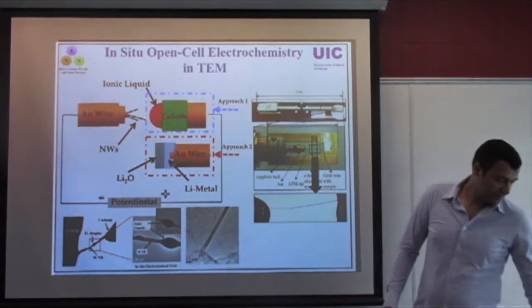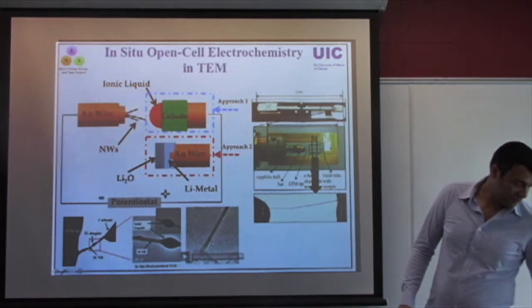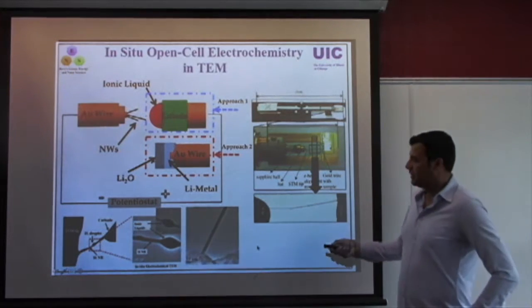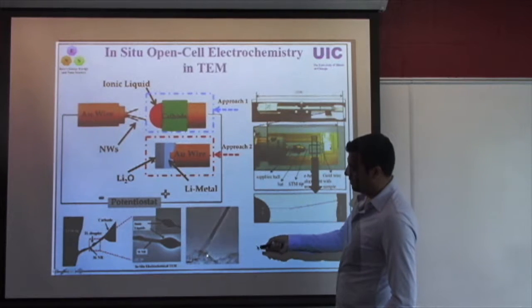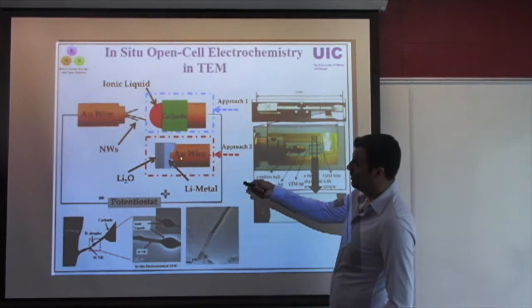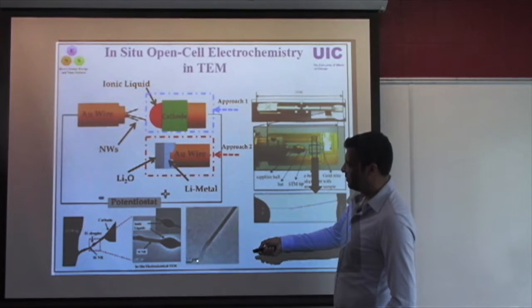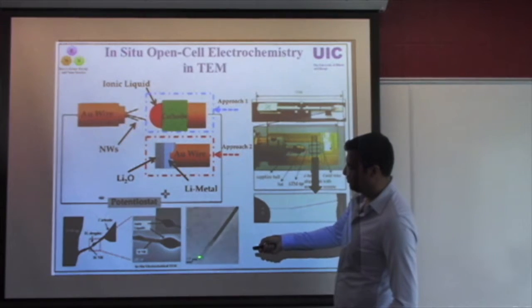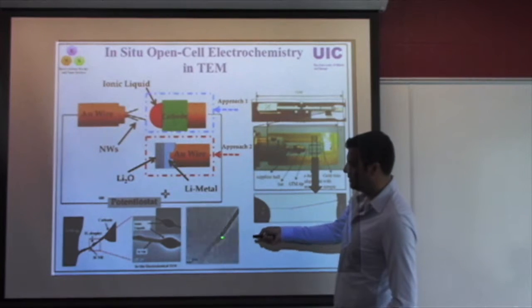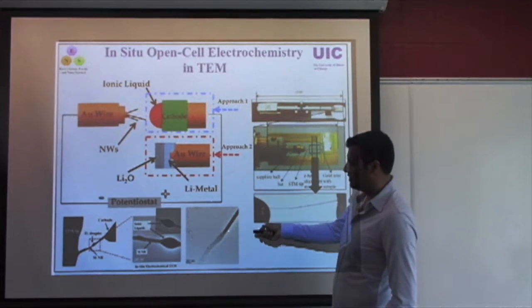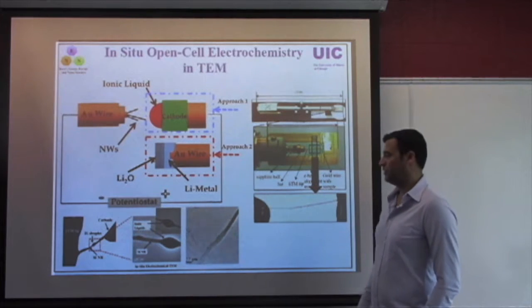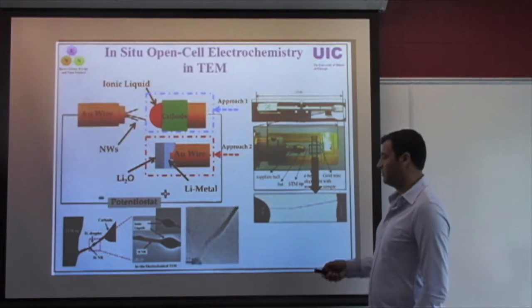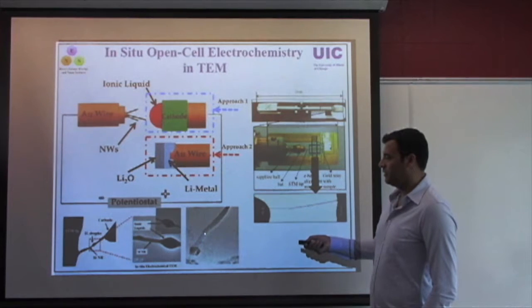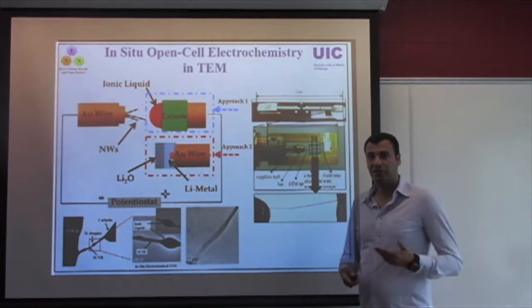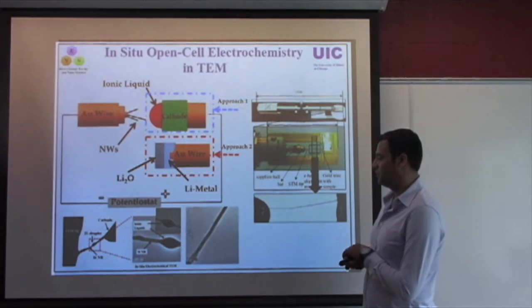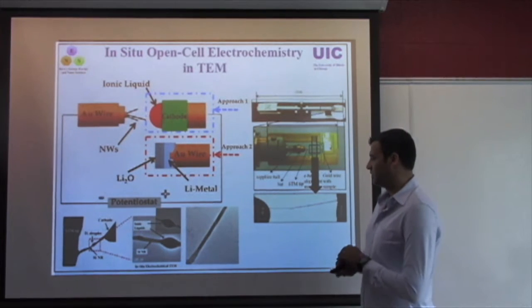This video runs successfully here. So it basically shows one example of a nanowire in contact with the lithium, something like this approach, where you're seeing quite clear changes in the material itself, and the progression of the interface toward the other contact of the electrodes. So that will result in some phase transformation, phase changes, which can be very useful for the fundamentals of the electrochemical reactions.